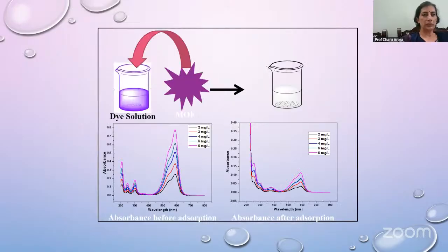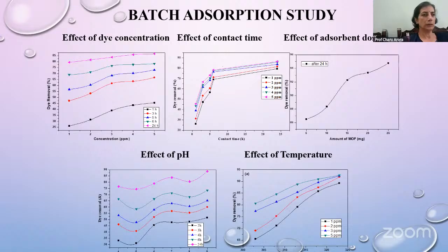And when the dye solution containing crystal violet and methylene blue was treated with this synthesized MOF, the dye was removed, as shown in these absorption spectra of different dye concentrations before and after adsorption. This slide is showing the effect of concentration, contact time, and dose. You can see with time, removal increases and equilibrium is attained around 24 hours. As we increase the amount of metal organic framework, the removal percentage increases, and maximum removal was observed at basic pH.